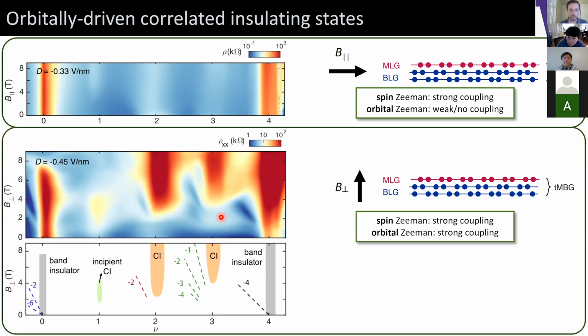When we apply perpendicular field, something interesting happens. At low field, there's also not much going on, but then abruptly correlated insulating states emerge in what seems like almost a first order phase transition at half filling, at three-quarters filling, around 2.5 or 3 Tesla, and then also an incipient correlated insulating state around quarter filling, although it's never fully developed.